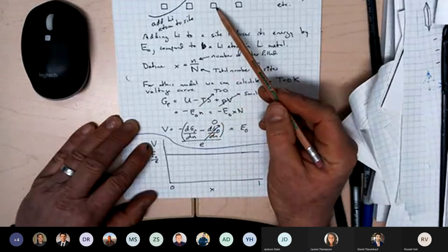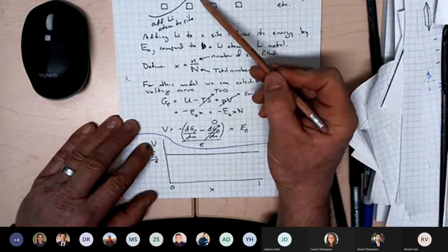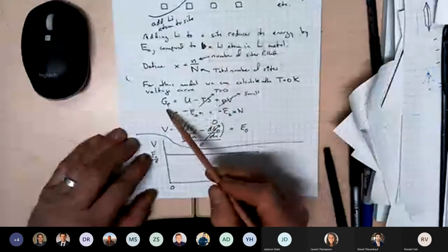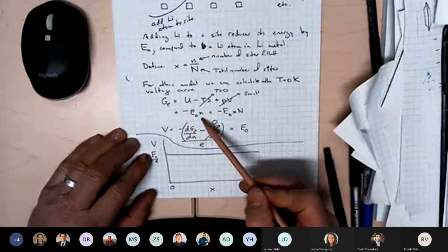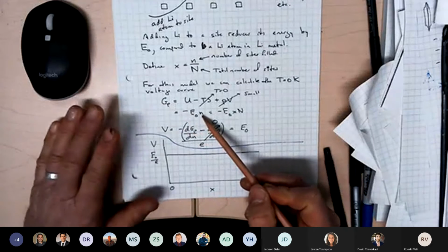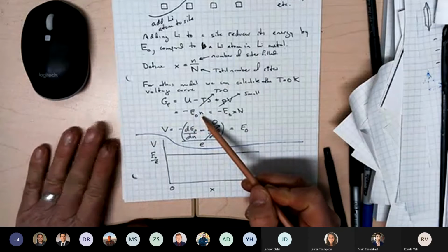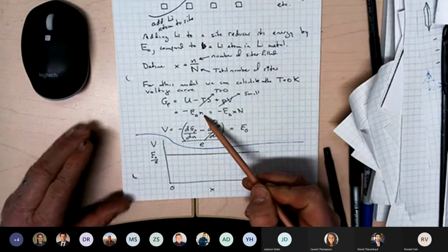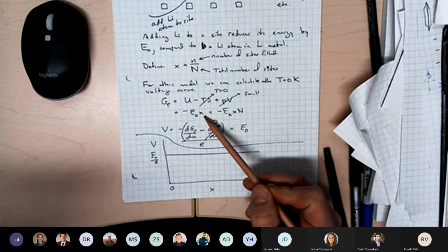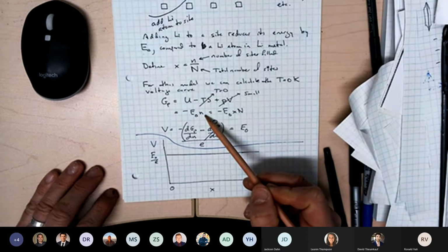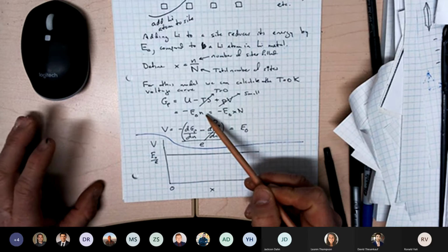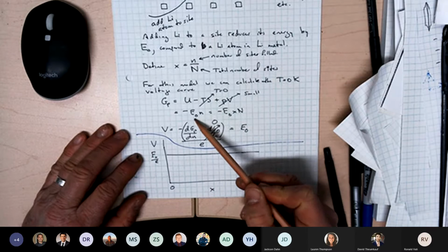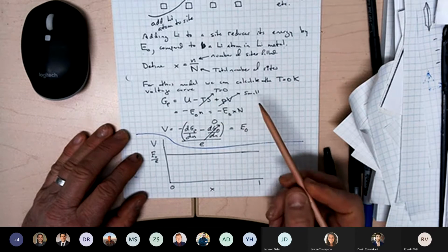Well, it's just E0 times the number of filled sites. That's what it is. So the free energy of the positive electrode is minus E0 times N. So all we're doing here is we're totally neglecting the contribution of the host itself, because we say the host doesn't change. When we add the lithium, the host doesn't change in a material way. The bonding between titanium and sulfur doesn't change effectively very much. We just say, put the lithiums in, and they have this binding energy minus E naught.